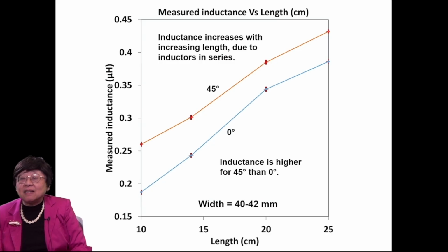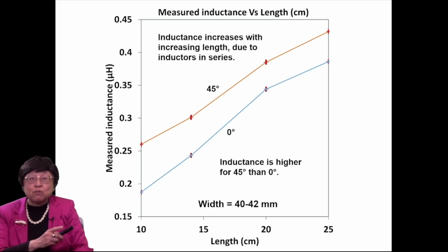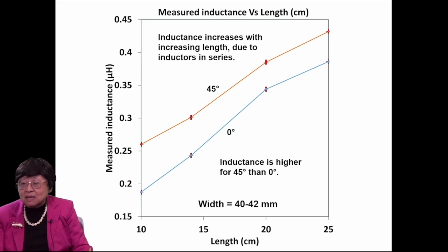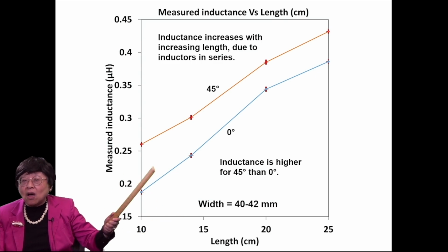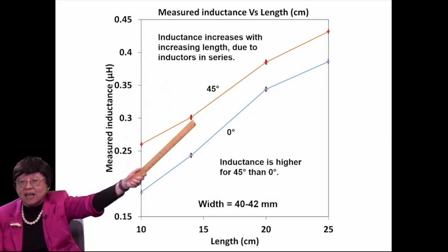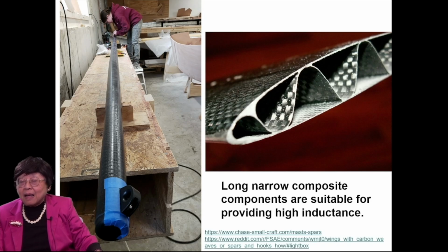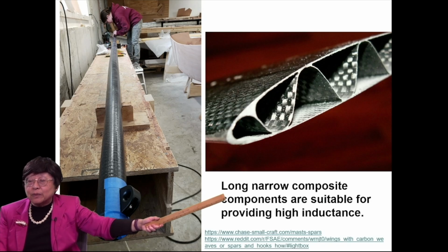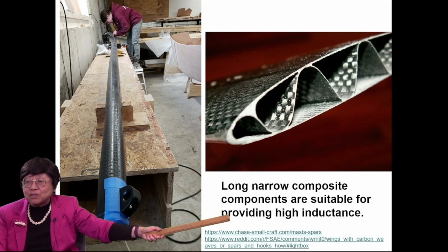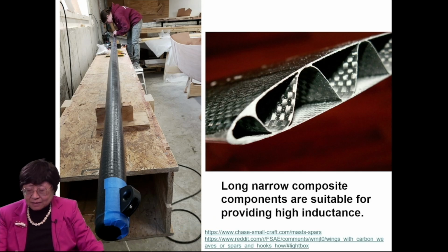And shown here is the length effect. The previous slide was the width effect. Now it's the length effect. The longer the length, the larger is the measured inductance because of inductors in series. And 45 degrees give higher inductance than 0-degree. And because of that, long, narrow composite components are suitable for providing high inductance.